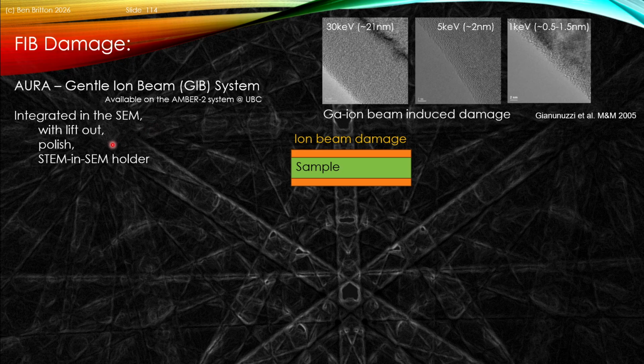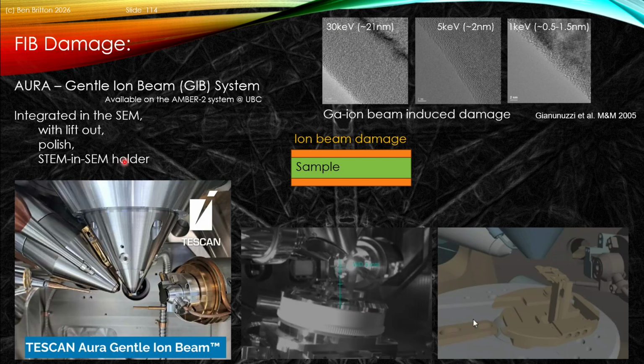And this is highly integrated to enable us to have lift-out, polishing, and STEM in SEM without breaking vacuum. So this is the system as shown from the promotional materials from TESCAN, but effectively we have the electron column, we have the gallium column, we have a manipulator needle, I think is this one, and then the GIS system. And then we have the Aura system that enables us to effectively open this aperture and insert an argon ion